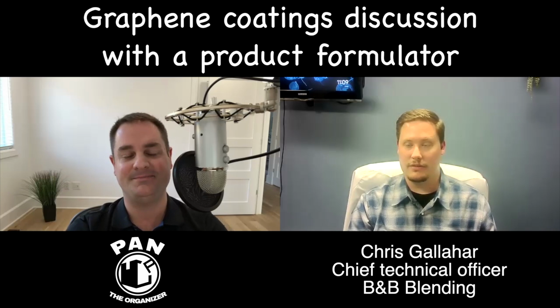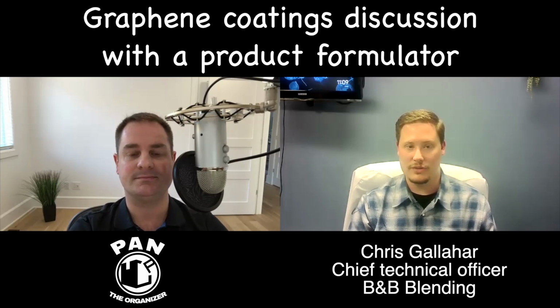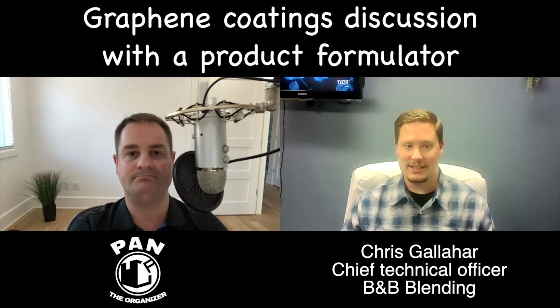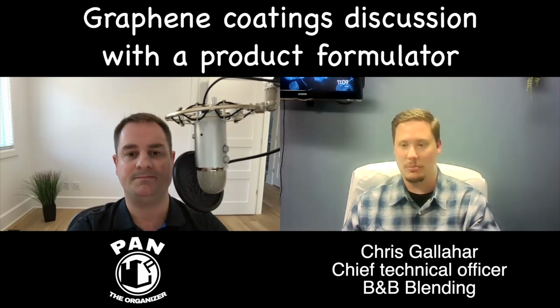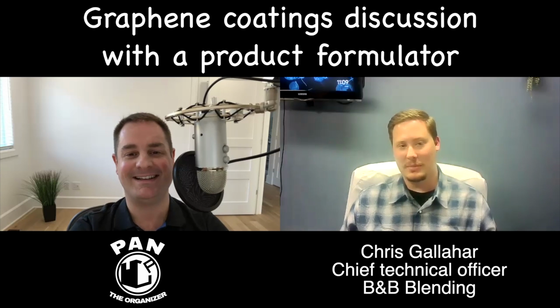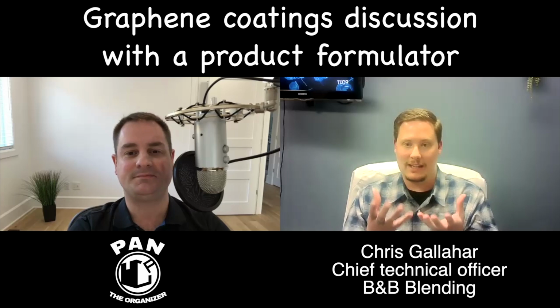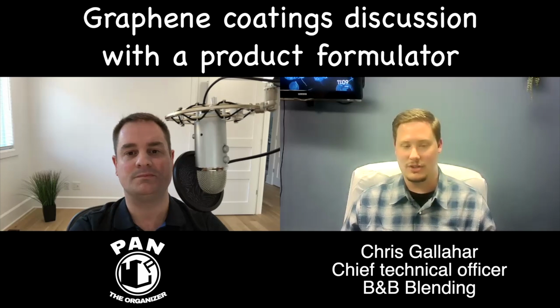Yeah, so I think certain degreasers are made with more novel surfactants that have more powerful emulsification. And so it seems like they clean and strip better, but the reality is they're just better at wetting. Exactly. When you get them on the surface, they're flattening the water, and everyone's like, we have a winner. And I'm like, the reality is, give it a month, and I bet you both of those panels pop back. The coating's not actually gone, because on a molecular level, you're going to have a hell of a time, without physical abrasion, stripping that coating, because it's molecularly bonded and protected at the reactive sites where it bonded from a degreaser stripping it off.